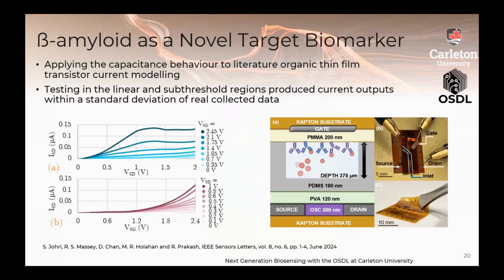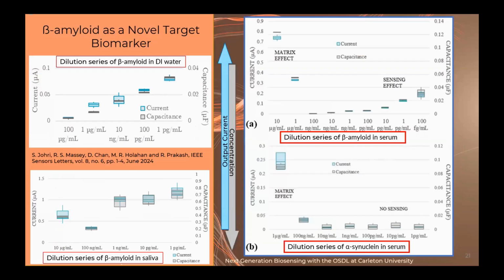So this is the integrated sensor structure, and during testing, standard transfer functions, IV responses. We have tested over a few hundred devices, so they're quite repeatable performance. In deionized water, obviously no matrix effect, so nice linear, log linear behavior. What is new here, along with the antibody-based biomarker, is we are looking at serum. So we are currently doing a biobank study with serum, but this is a preface to that, where we look at different dilutions of serum.